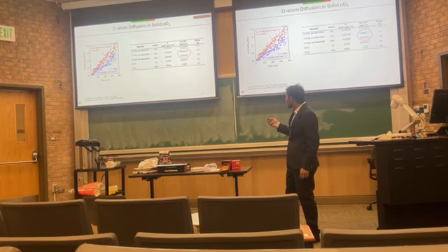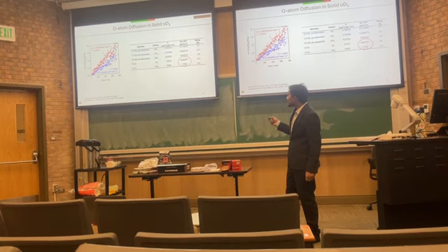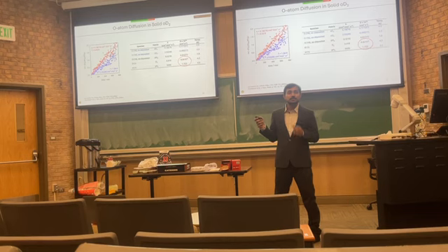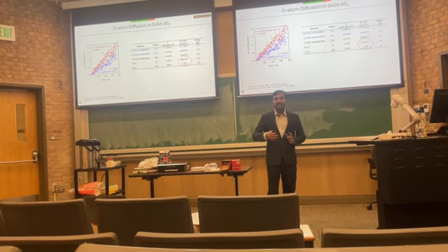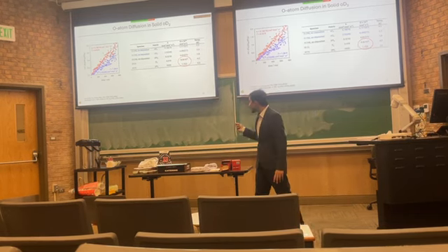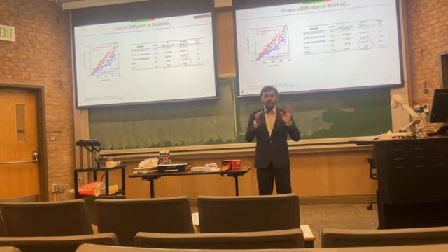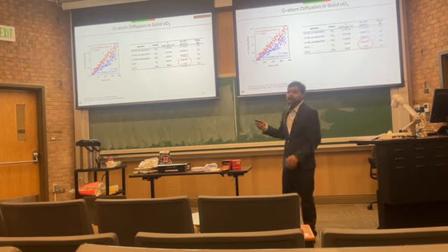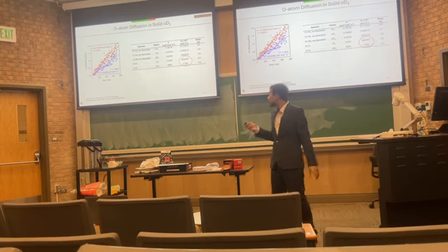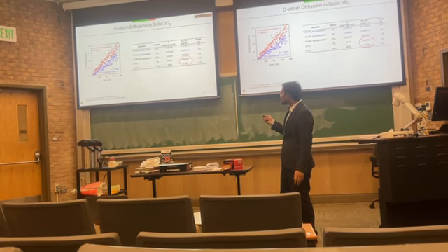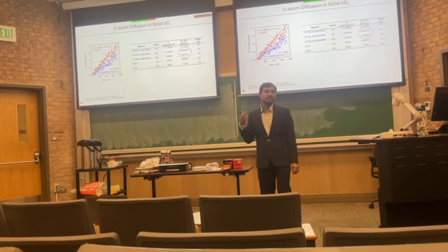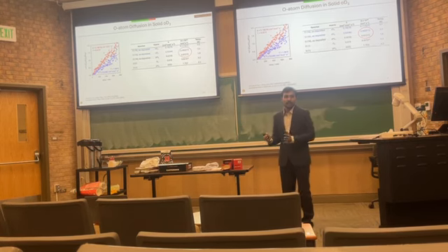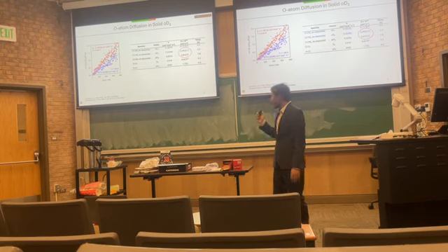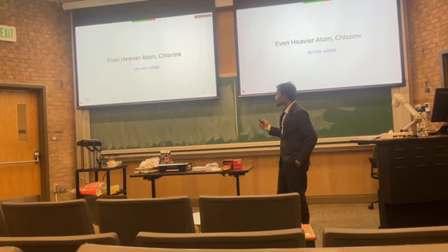But if you remember, for deuterium and hydrogen, from parahydrogen to deuterium, it was 1.7 and that was 10 to the power minus 5. So now we're getting something completely different. What they got for deuterium was much slower, like 5 orders of magnitude slower. But what we see is not a big change, just one order of magnitude slower. So that's a big question, what is going on? We'll talk more on this.